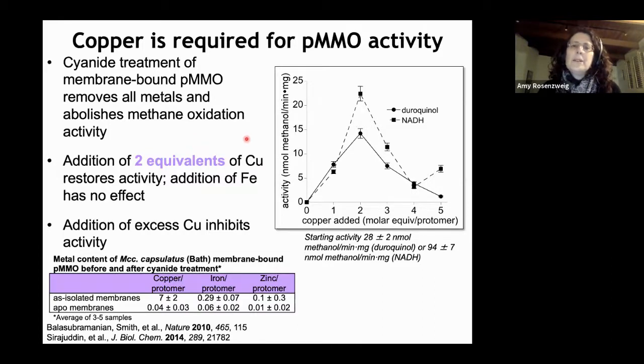And shown on this slide is an example of an experiment that we did many times to address that question. What we do is we take what I call the membrane-bound PMMO, and that's the isolated membranes from the organism before we solubilize with detergent or purify or anything. And those membranes are probably 80% PMMO. We use those for studies that involve measuring enzyme activity, because those are more active than the purified protein. And what we do in these types of experiments is we treat the sample with cyanide to remove all the metals, and that abolishes the activity. So on this plot here, we have no metal present and we have no activity. And then when we add copper back, we can recover activity, and that maxes out at about 2 coppers per protomer, which is the structural unit I showed you on the last slide.